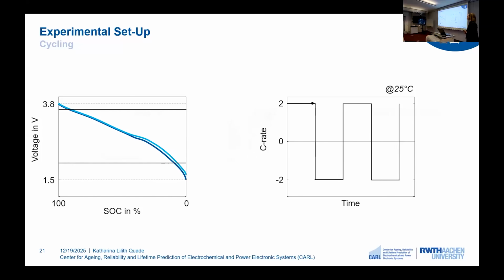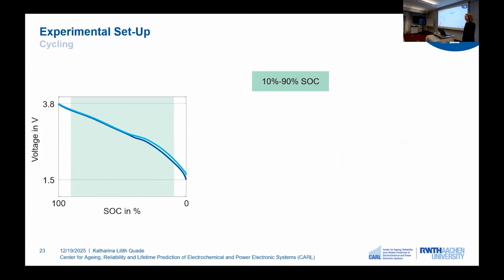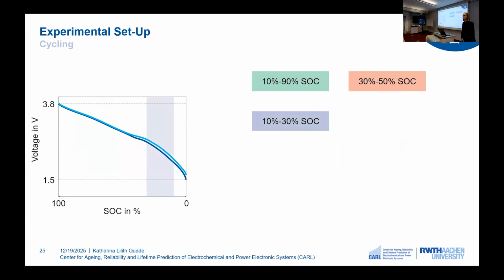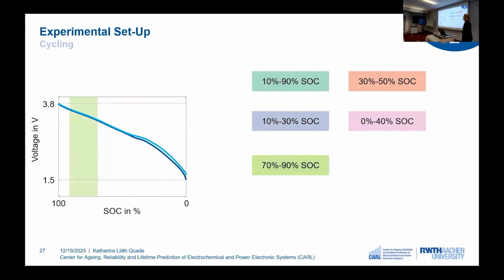Let's have a closer look at how this works. So we charge our cell with 2C until we reach the upper limit of the charge curve, and then we discharge our cell again with 2C until we reach the lower curve. And this corresponds to the first condition, in this case 10 to 90% SOC. We also have another condition that is in the mid-SOC range, 30 to 50% SOC. And we have also 2 conditions for the lower SOC cycling. Here, 10% to 30%, increasing the depth of discharge 0% to 40%, and also mirroring this for the upper SOC. Here we can see the condition 70 to 90%, and again, increasing the depth of discharge, we have the condition